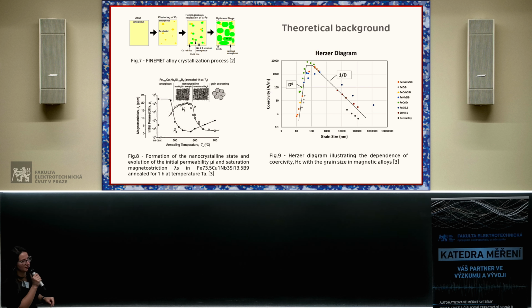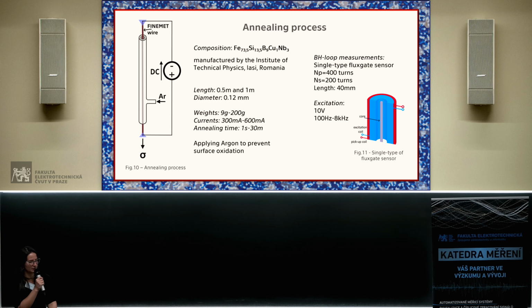In picture 7, you can see the process of crystallization, because it's a step-by-step process, and we need to anneal it until some temperature. If the annealing is too short, the material still didn't crystallize, because grain growth takes some time. And also, we shouldn't exceed some point of annealing because domains will be too big, coercivity will be too high, and permeability will drop as well. So we have a flash annealing process, and it means we should do this really fast.